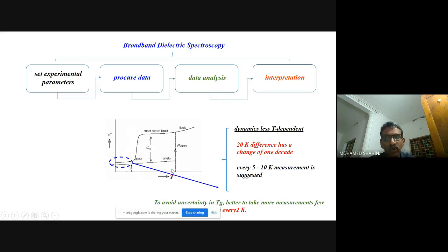That is the strategy you have to follow. Otherwise, we will be in an uncertain condition whether the sample is degraded or not. This you have to do, otherwise we will not accept your data for publication. Or one other option is that you have to take a fresh sample and do these exercises and do an FTIR or NMR experiment, and make sure that your sample is not